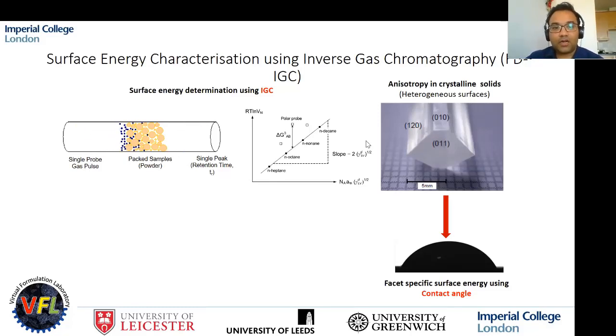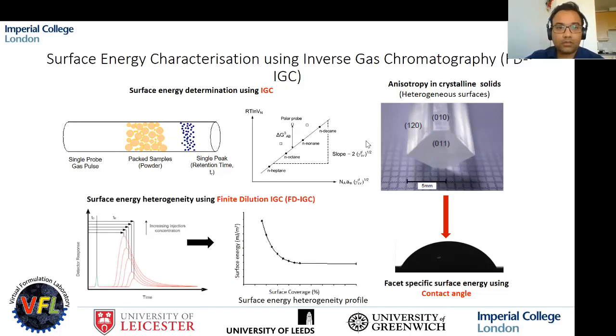Now, the solids have energetically heterogeneous surfaces. So depending on different planes, different facets, they may show different energies, like, for example, contact angle measurement. Next, please. Yeah, so here we are using a new approach called finite dilution inverse gas chromatography to determine the surface energy heterogeneity of these solids. So we get data in the form of surface energy as a function of surface coverage. Next, please.